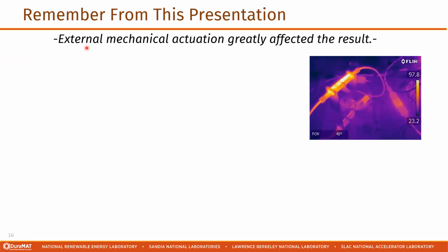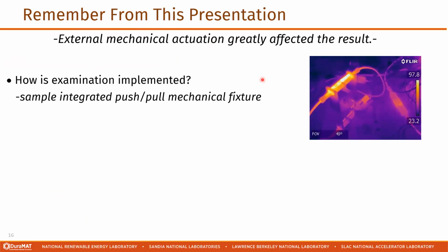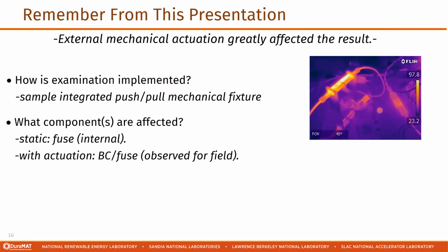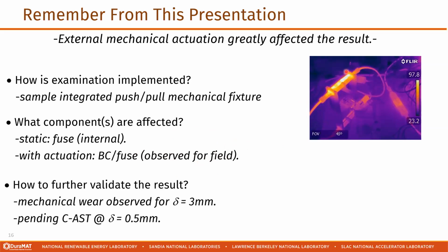So, yep, hopefully you'll remember there's a big influence of the mechanical actuation that we saw in the benchtop experiments. And then we used a push-pull mechanical fixture as part of the experiment, right? That's what was providing the mechanical actuation. There were different components that were affected in this experiment. For the static assembly, they were affected at the fuse internal to the components. Once we added actuation, this was more like at the branch connector to fuse junction. This is also the same location. There's evidence of this in the field failed samples, right? Like where it's hot and melted and deformed is at that same location in some instances.